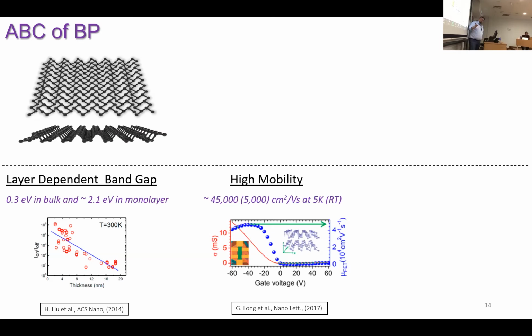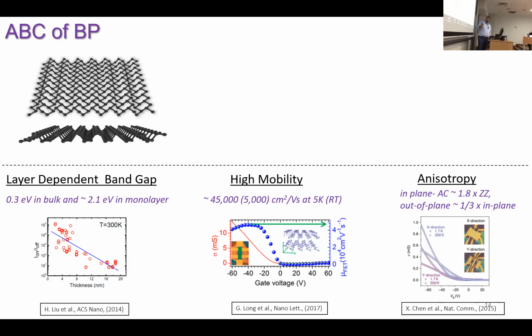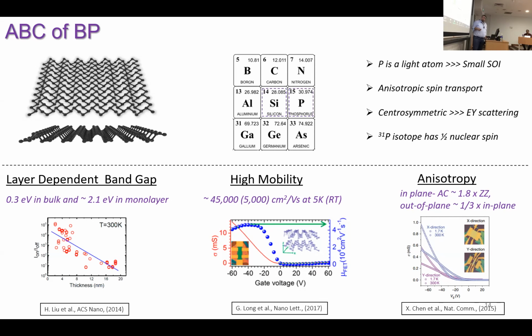And the second thing, I think this is one of the most important reasons why we chose to work with black phosphorus, is it has extremely high mobilities. The mobilities in black phosphorus approach 50,000 at low temperature, and at room temperature it's like 5,000. These are very comparable mobility values to what we are using in graphene spin valves. And the last reason why it's interesting is that it is anisotropic. The material is highly anisotropic. It was shown for charge transport and thermal transport. The material is already anisotropic in plane, along the armchair direction. Here is the armchair direction, and if, for example, charges are diffusing towards here compared to here, their mobilities are different. So that's also another thing which makes this material quite different compared to other usual materials.